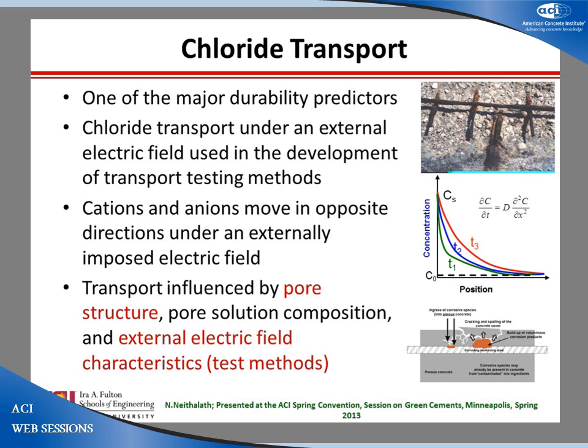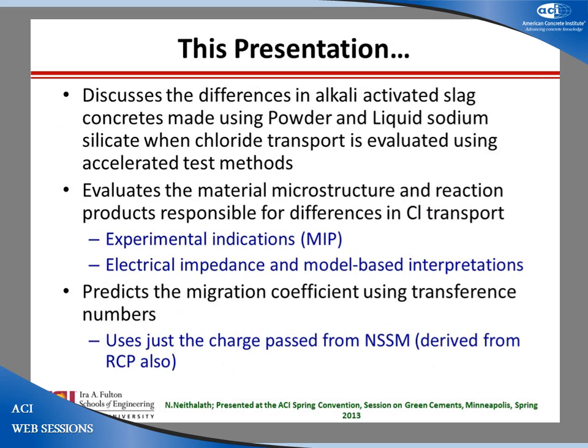So basically we know that chloride transport is influenced by the pore structure, pore solution composition, and the external electrical field, depending on what kind of accelerated test method you use for chloride transport. So this presentation looks at two different types of activating alkalis. Typically, sodium silicate or potassium silicate solutions are used because they are better activators. But from the point of view of constructability, powders are also better because you can then make a one-component, just-add-water kind of system. So we're looking at blends where you can use powder activator, blend it with the slag, and have a one-component system. But how does the microstructure change if you have that kind of activation?